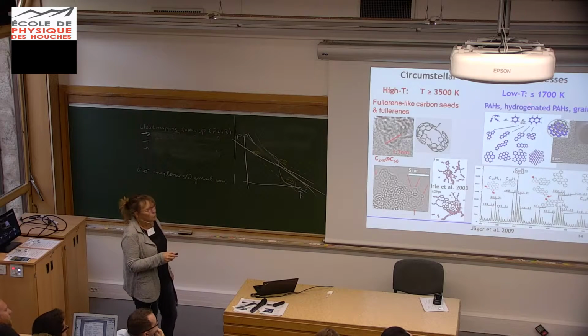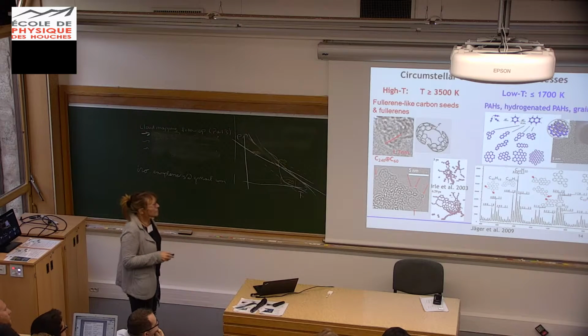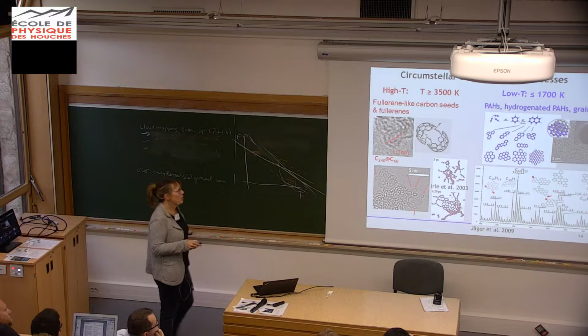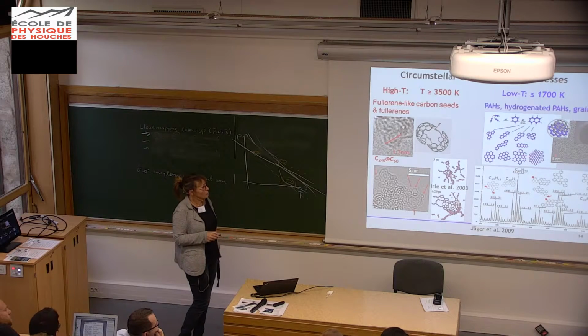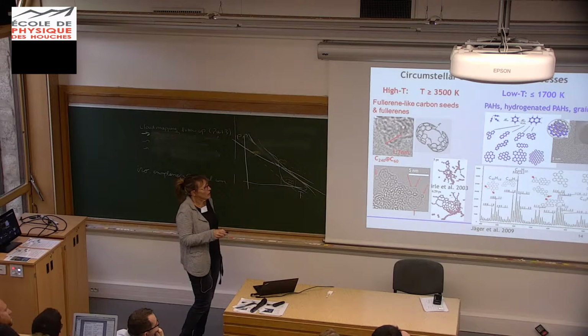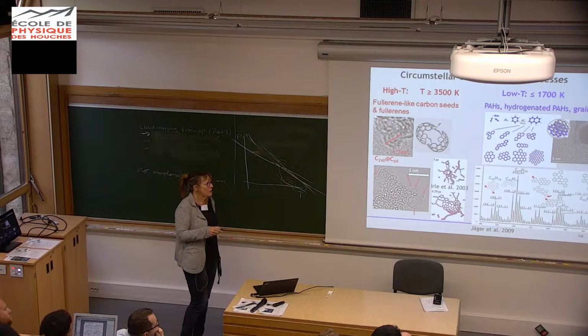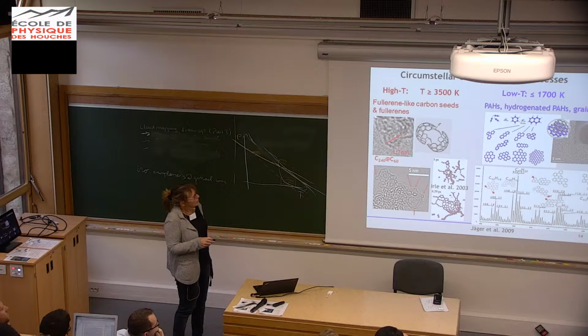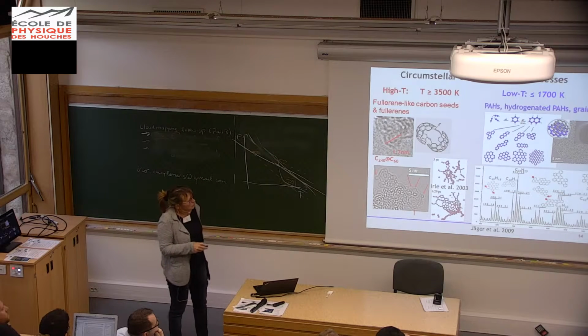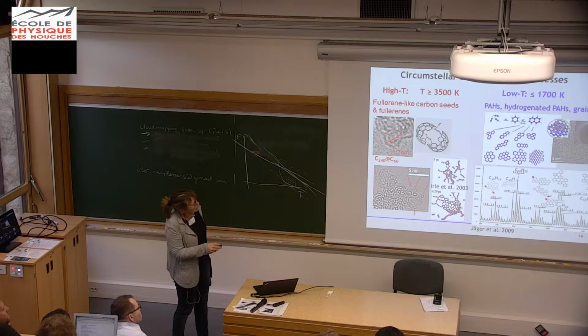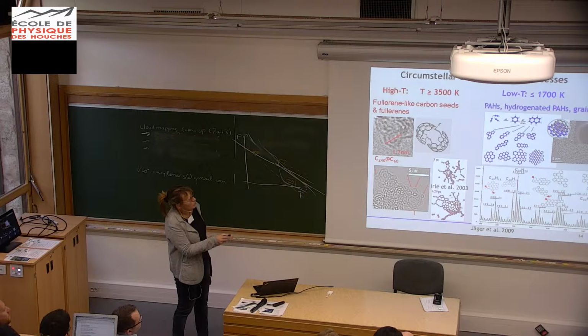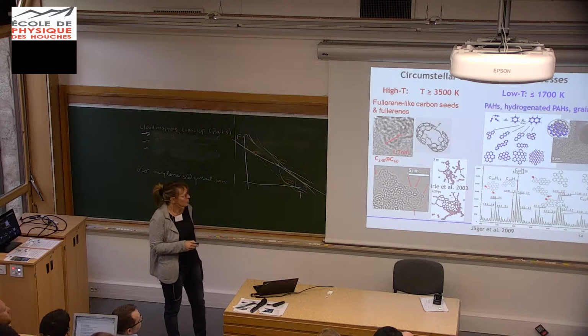If you go to lower temperature, lower than 1700, you can see that only PAHs play a big role. Here we have probably nucleation seeds which are made of clusters of PAHs. The grains you can see are made of really large and flat PAHs. In addition to the grains, in such low temperature condensation, we get always a lot of PAHs.